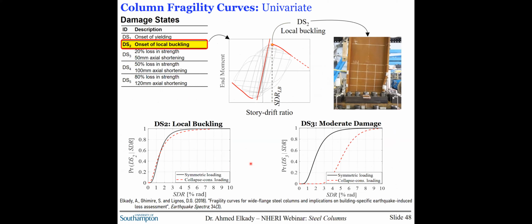So I'm close to the time. The last thing I'm showing, which was the last part of the research, is the development of damage fragility functions. The development of such functions was feasible given all this new test data, and this can, of course, be used for loss assessment studies and such. We developed univariate fragility curves, as the ones you see here, that take into account the loading history effect. For local buckling, the difference between symmetric loading and collapse loading won't matter a lot. But after that, once local buckling progresses, the probability of damage changes substantially based on the loading history the column is subjected to.